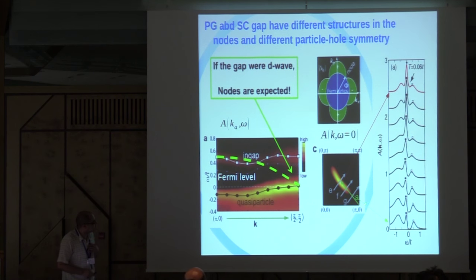And this is the antinode, and this is the node. And you see how the spectra look. There is a gap. There is a peak that is already formed, but the peak is shifted to negative frequency here. So there is a gap at the Fermi level. And when we move from the antinode to the node, the peak moves and comes to the Fermi level. And at this point, you form the arc. So this is what the pseudogap is in cluster DMFT. All right. So in a d-wave superconductor, what we expect is to have nodal points, points in the diagonal of the Brillouin zone where the gap goes to 0.